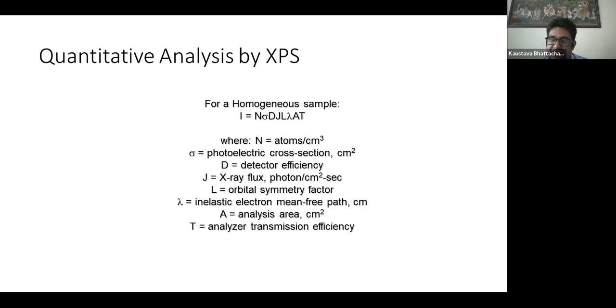It also depends upon the orbital symmetry factor, and upon the inelastic mean free path. Basically, if an electron is ejected, it should reach the detector directly. If there are other inelastic collisions, we should take those into the picture as well. It also depends upon the analysis area and the analyzer transmission efficiency. All these together give me the total intensity of the peak.